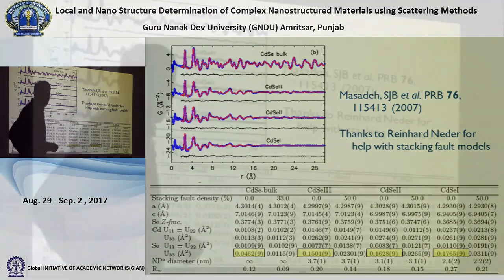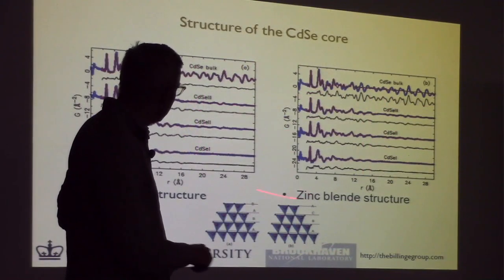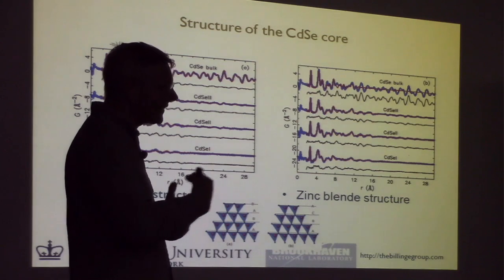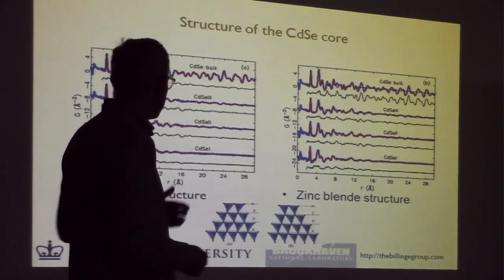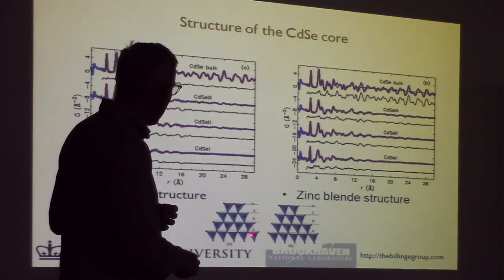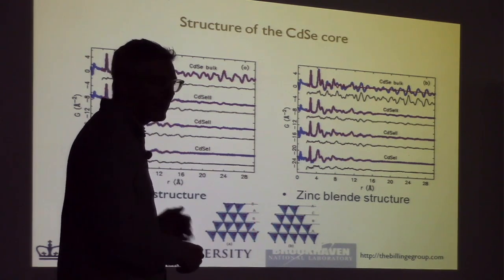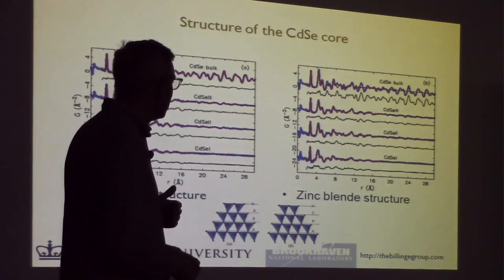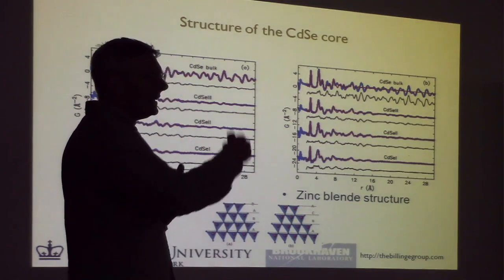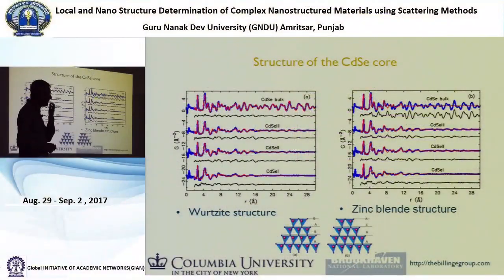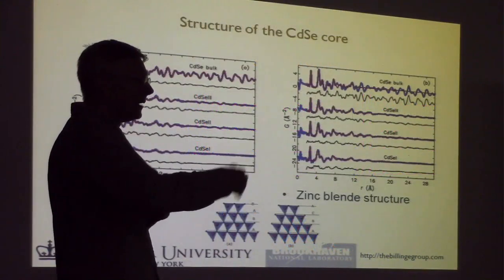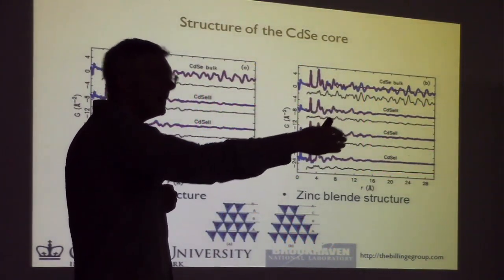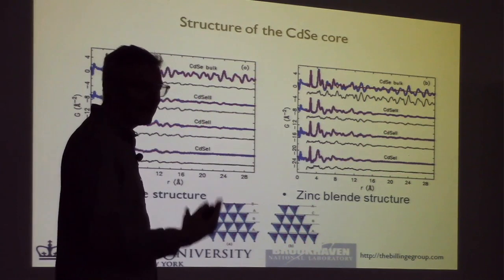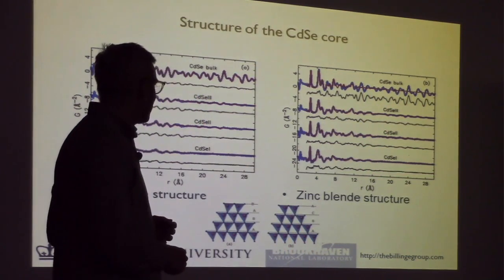So actually, we can go back and look at what's the difference between these two structures. These have a particular stacking along the C-axis direction. Wurtzite is A, B, A, B, A, B stacking. And zinc blende is A, B, C, A, B, C stacking. So what you can have in these materials is defects. You can have a material that's zinc blende that goes A, B, C, A, B, C, A, B, C, A, B, A. That was a mistake. That's a stacking fault. So these things can have stacking faults.